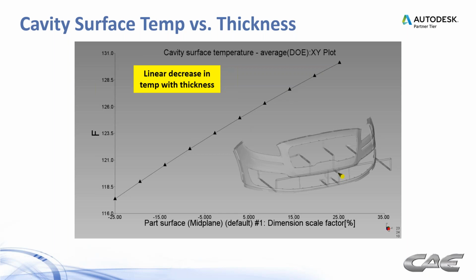On the cooling side of things, we tend to have a linear decrease in temperature with the thickness. So as those thicknesses come down, this is where we see benefits, right? And it tends to come down linearly. And then what I found over the years is that for every degree in temperature that we reduce something, it equates to roughly a second saving in cycle time. So that's how to look at this. So notice when we go down to like a 15% decrease in the wall thickness, we might be saving up to 5, 6, 7 degrees in temperature, which is going to equate to that 7-second cycle improvement.